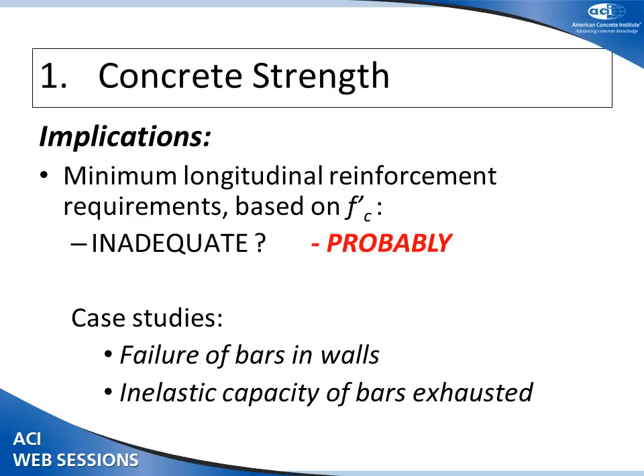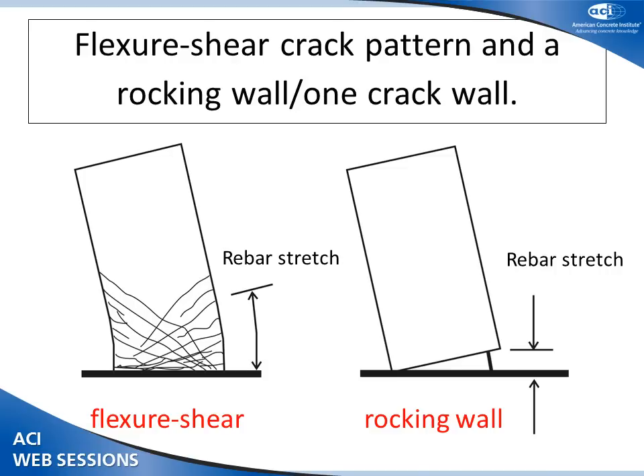The implication is: are the minimum longitudinal requirements in our standards sufficient for the real concrete, as against the lab concrete that we're dealing with in our labs and that the equations are quantified against? As a general rule, the minimum steel contents we spec, particularly in walls and some beams, were not enough to start with. And then if you add in the fact that the tensile capacity of the concrete is significantly larger, you find that we do not have enough longitudinal reinforcement to form a distributed crack pattern and spread the plasticity. Any crack, might be one or two cracks, opens up, and that plasticity is confined to a short length of bar. And here's a couple of case studies.